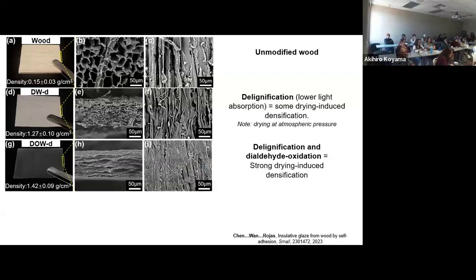But if we do the dialdehyde oxidation that I introduced in the previous slide, what you will see is a further gain in density, and now you see that the material becomes transparent. That's because all the air is being expelled out, then the material bonds stronger. There are fewer solid-air interfaces. That means less scatter of light, and that means light comes in and leaves the material. Transparency. Cross-section, plane view, gray material. And strong, dense, strong, and transparent.